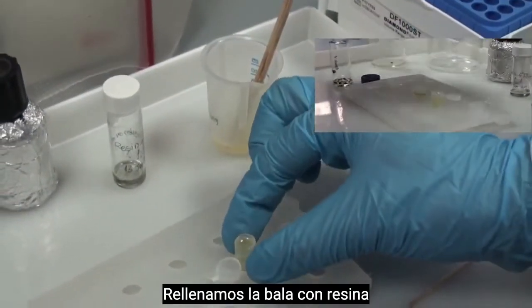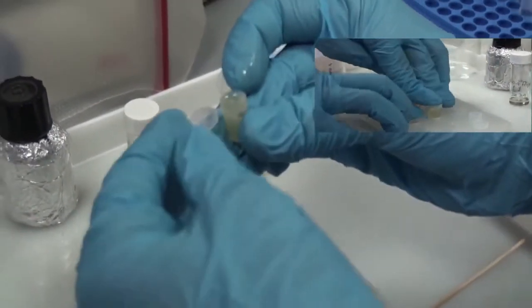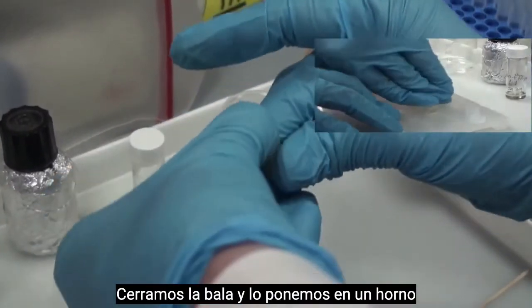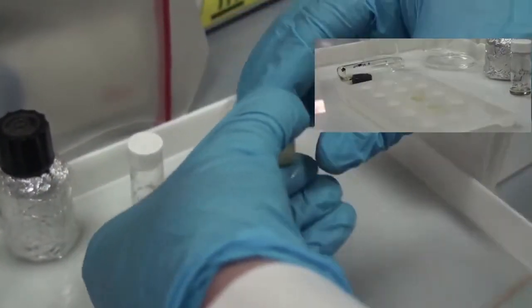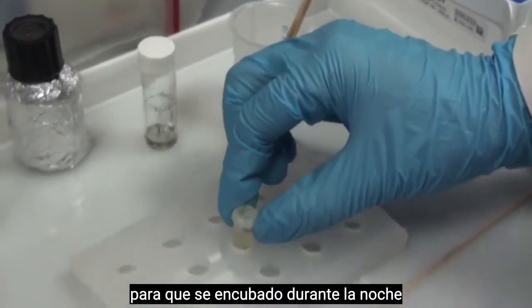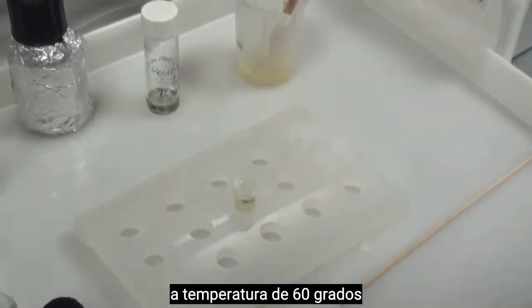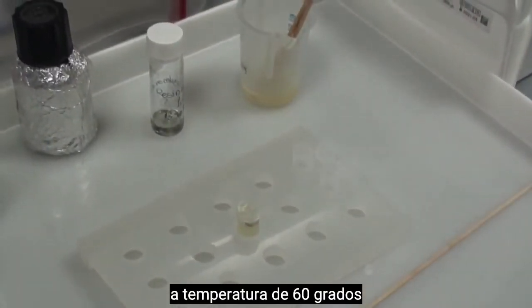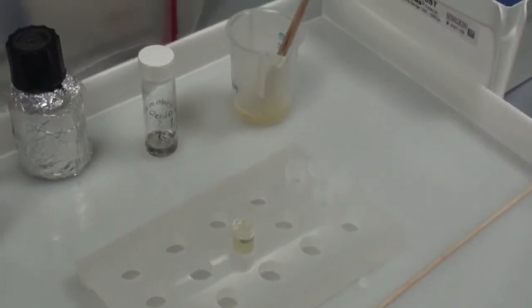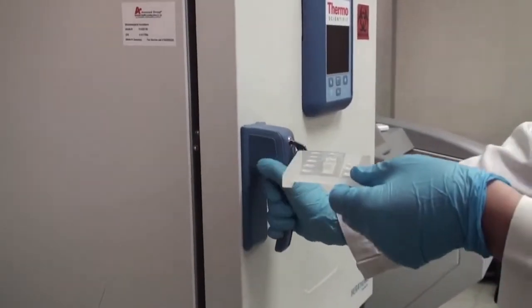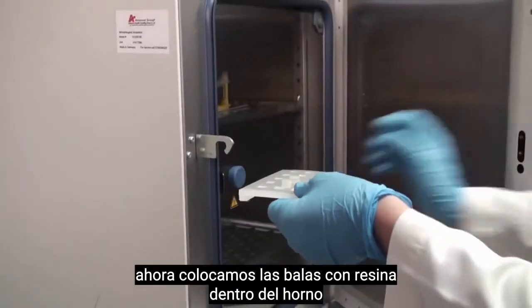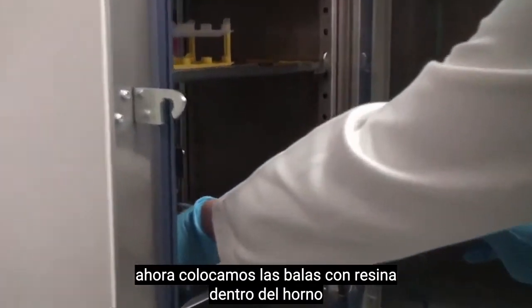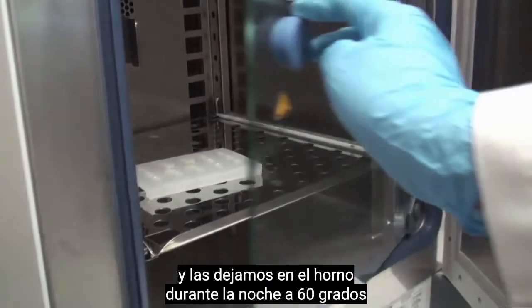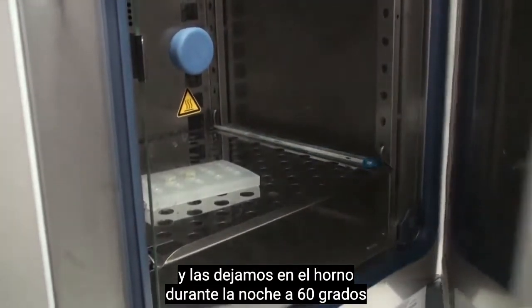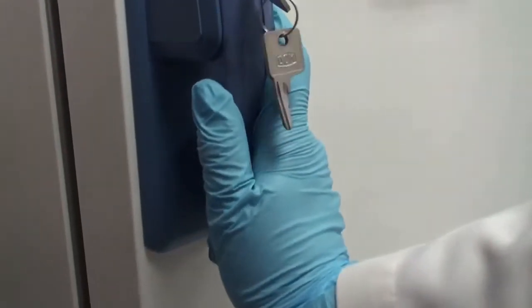We fill the bullet with resin, close the bullet, and it goes into an oven to be incubated overnight at a temperature of 60 degrees. Now we will place our bullets filled with resin inside the oven and leave it in the oven overnight at 60 degrees.